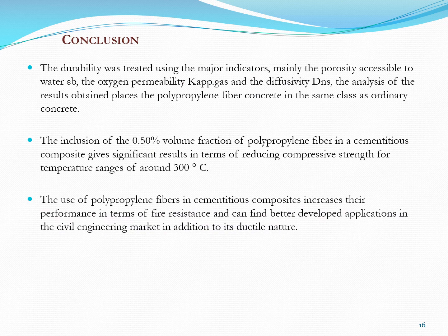As the conclusion, the durability was treated using the major indicators. The analysis of the results obtained places the polypropylene fiber concrete in the same class as ordinary concrete. Secondly, the inclusion of the 0.50% volume fraction of polypropylene fiber in a cementitious composite gives significant results in terms of reducing compressive strength for a temperature range of around 300 degrees Celsius. On the other hand, the use of polypropylene fibers in cementitious composites increases their performance in terms of fire resistance and can find better development application in the civil engineering market, in addition to its ductile nature.